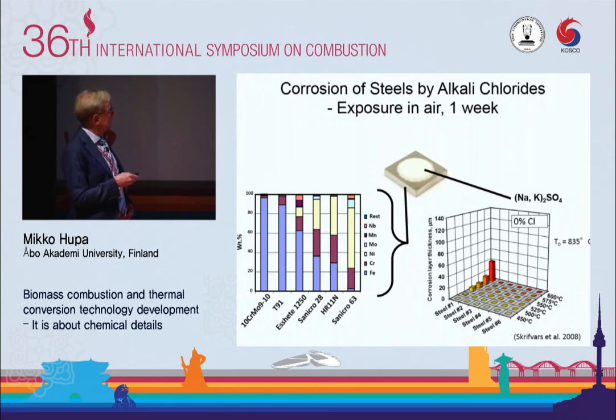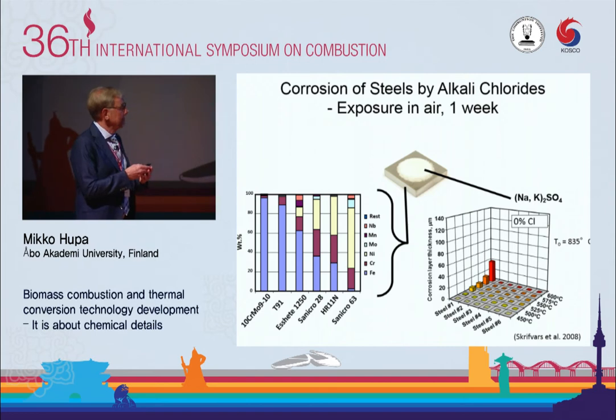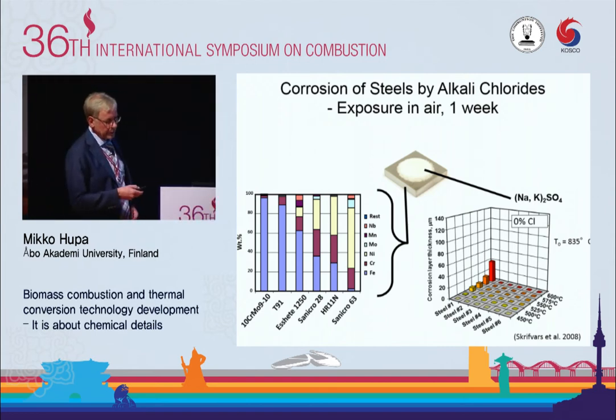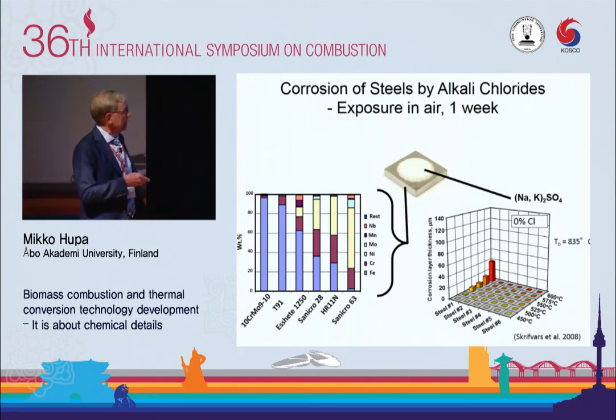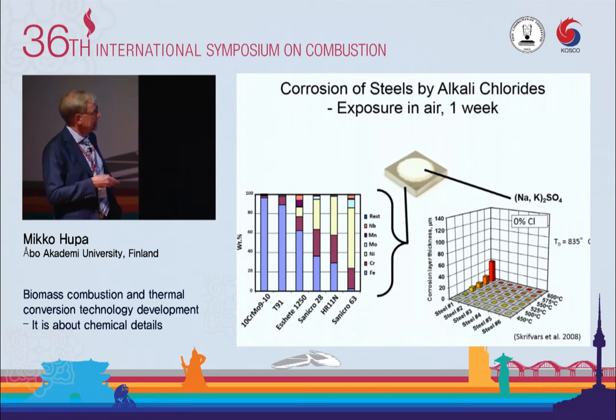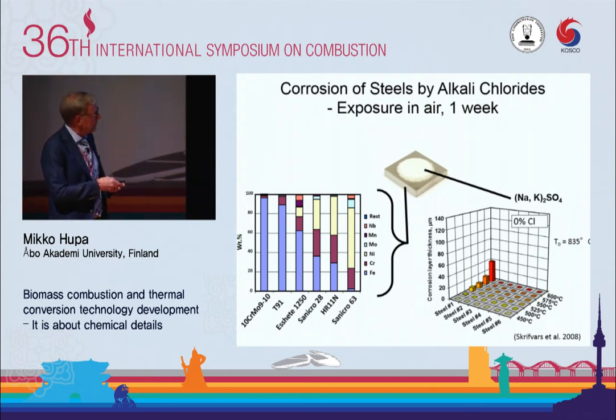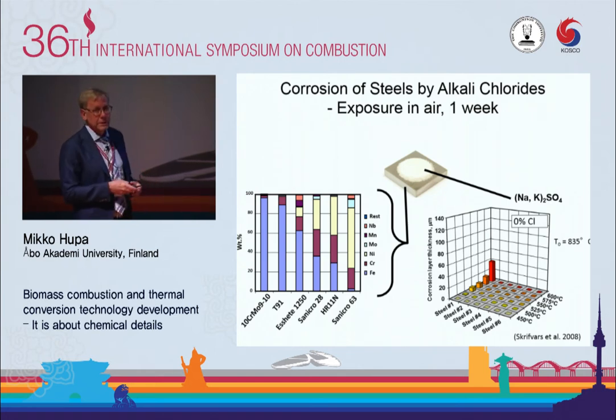These are austenitic stainless steels, and these are high alloy nickel materials. It's good to know here that if this costs 1, this will cost about 40. So they are extremely expensive ones, because of the quality of the steel and the nickel content. Then we did a full series of temperatures, 450 to 600, with all these steels. In fact, our students did all these tests, but under these conditions, when we used only alkali sulfate as base material, no chloride yet, we got no corrosion for most of the steels, except steel number 1, which is the low quality. And this is not caused by the salt. This is just oxidation of that material at high temperatures. But you could see that if we have no chlorides, we could easily have material temperatures up to 600 with all these materials without any problems.